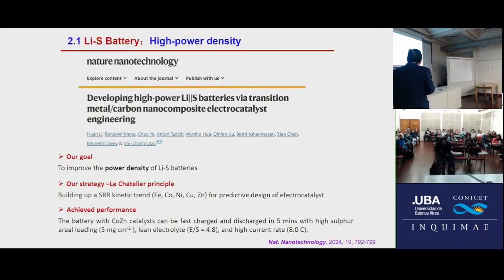Okay, in this research, first we use different metal catalysts to study the kinetics. First we use Le Chatelier's principle to establish a relation between kinetics, the reaction rate, and the polysulfide concentration. After that we establish kinetics and material structure. From the equation we found that the CoZn catalyst has the best performance. We can finish charge and discharge in 5 minutes. Okay, this is very fast, right?